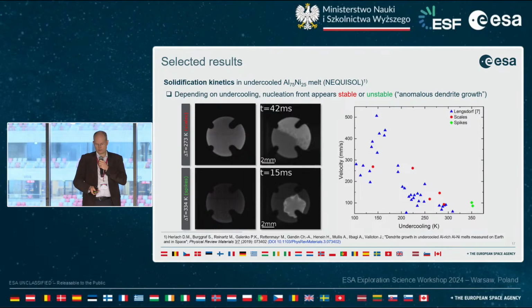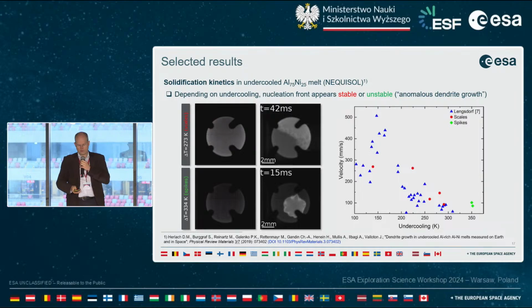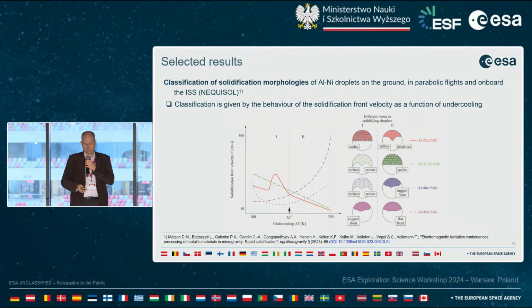So you see this recalescence front, the bright front that is propagating in the sample when it's crystallizing. And you see the different shape if you have the different undercoolings here. In particular, you see this kind of washed-out wavy behavior at the low undercooling. When solidification velocities were plotted as a function of undercooling, they showed an unexpected, anomalous behavior. There was a lot of discussion about this, and it can be understood now by looking more deeply into the modes of solidification, and they are changing in relation with undercooling, but also in relation with composition.